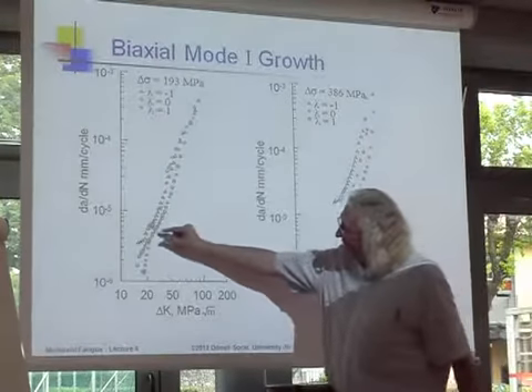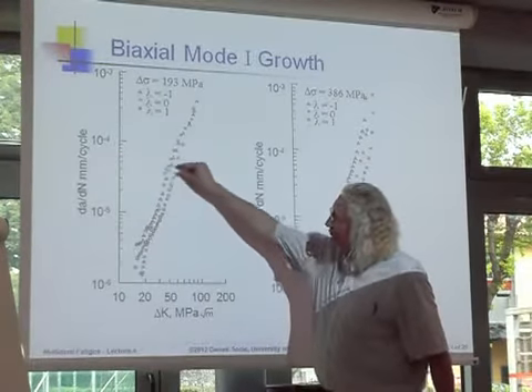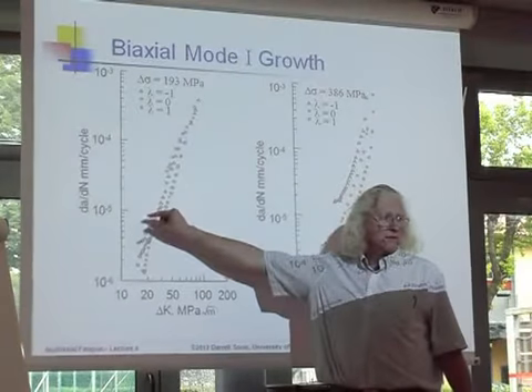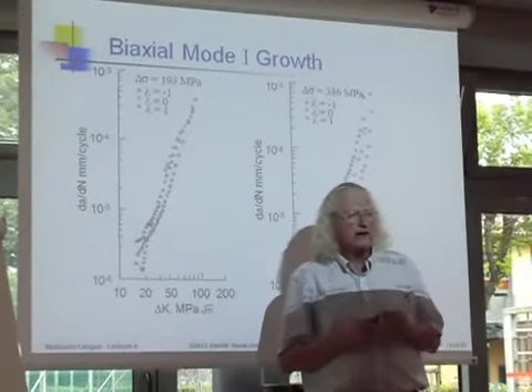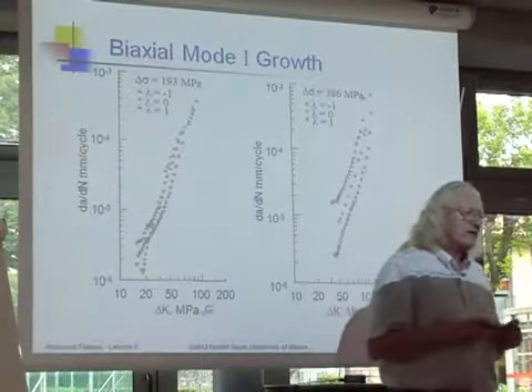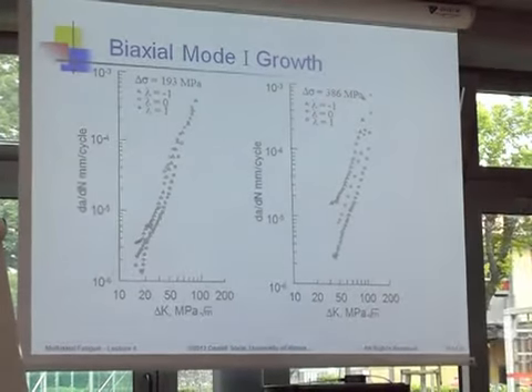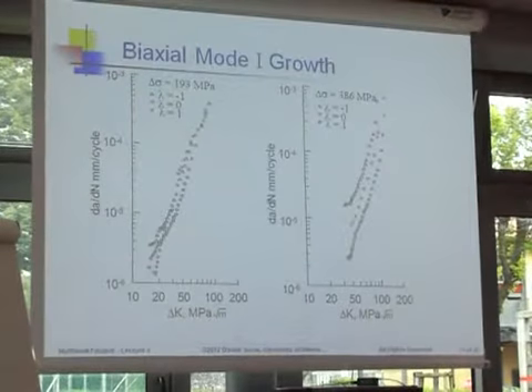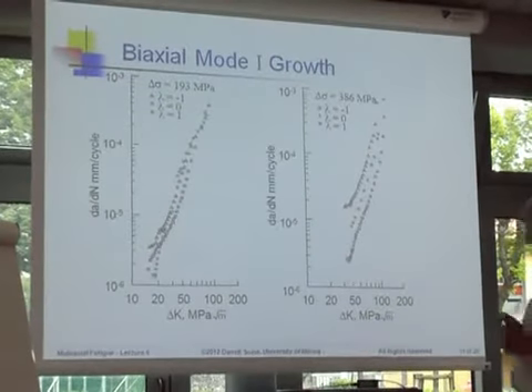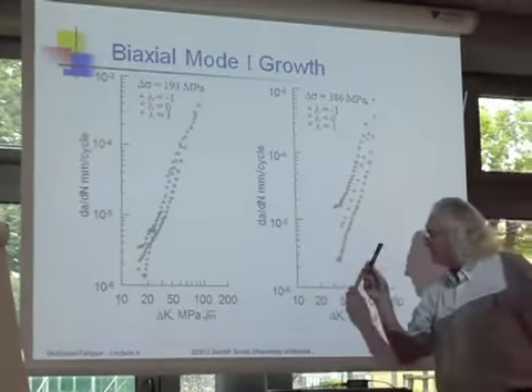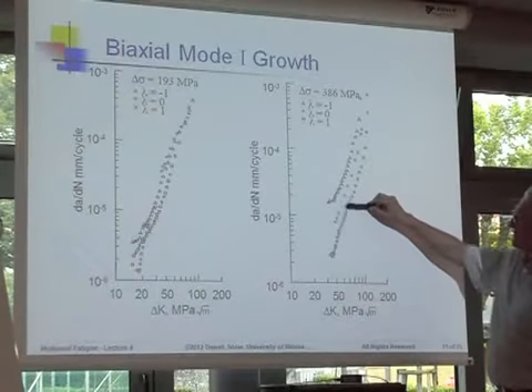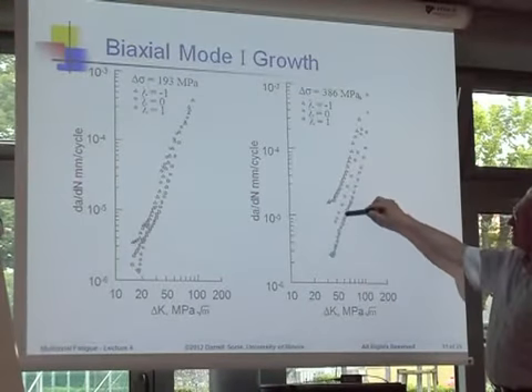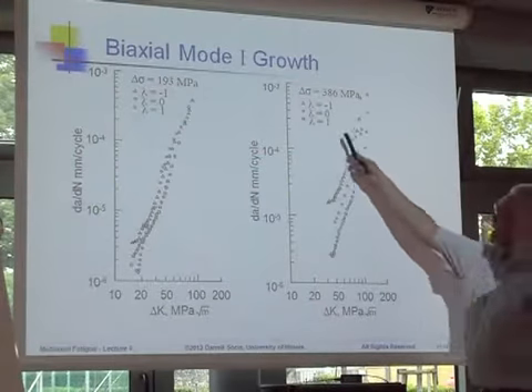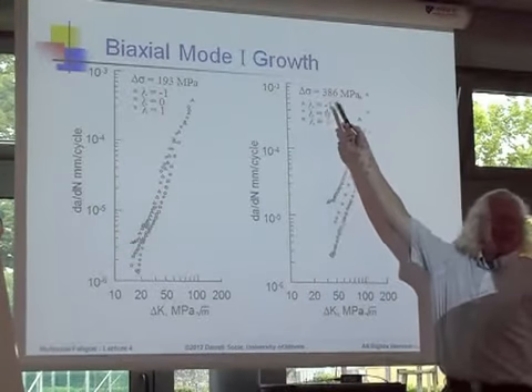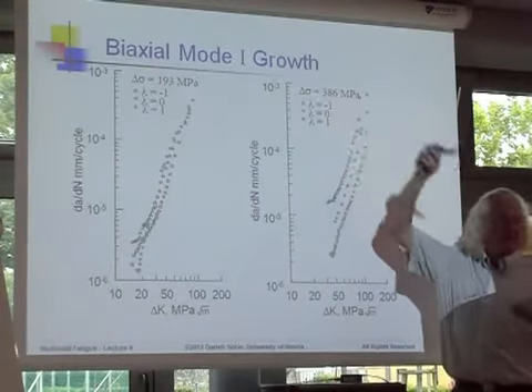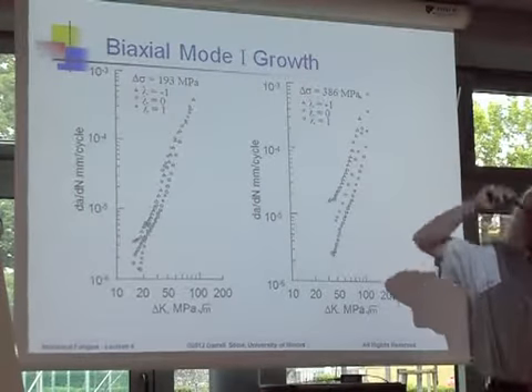So maybe this difference is only a factor of 2 in the growth rate. Well, if there's not a large effect, chances are there's not a lot of research. If you increase the stress levels, if you double the stress levels, then you can start to see some differences in the growth rates, but that's only as you go to stress levels that approach the yield strength of the material. So now you have net section plasticity concerns.